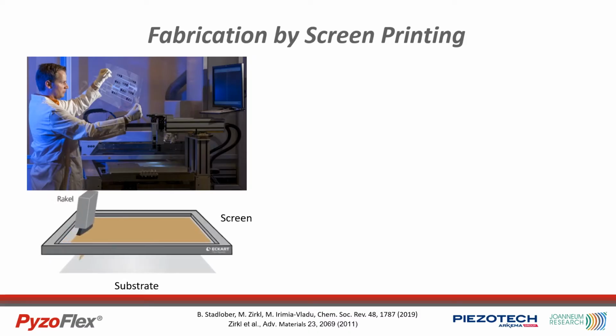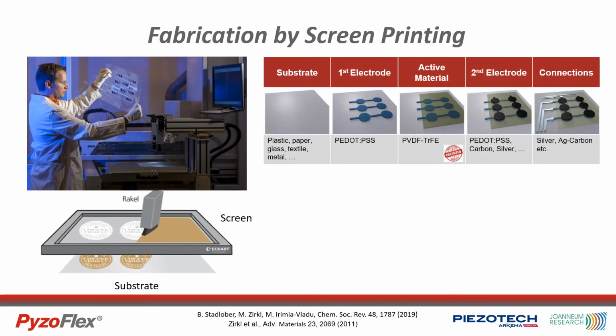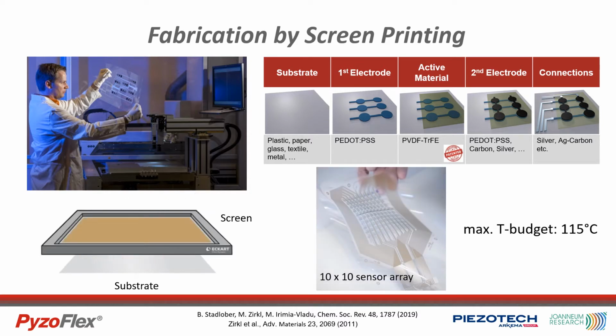We fabricate the Pyzoflex film by screen printing the transducer pixels on the flexible substrate sheet, and we can do that in formats up to DIN A3. Each pixel has the active material, the PVDF-TrFE layer, sandwiched between electrodes made of PEDOT:PSS, which is a conductive polymer, carbon or silver. Here you see a PET film with 100 tiny sensor spots in an array configuration with PEDOT:PSS electrodes in this case and silver interconnection lines.